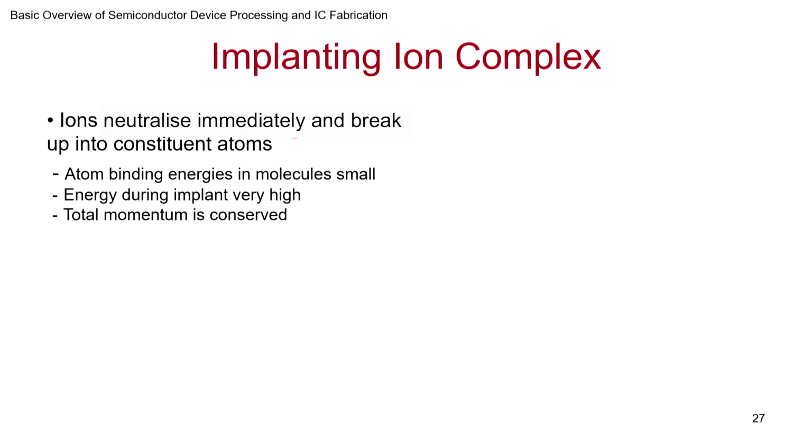And not just that, if a polyatomic ion complex is coming, it ends up breaking up, because the atom-to-atom bond is a few electron volts, while the kinetic energy that it has is thousands of electron volts. So in comparison, when it is crashing, all these things go apart.